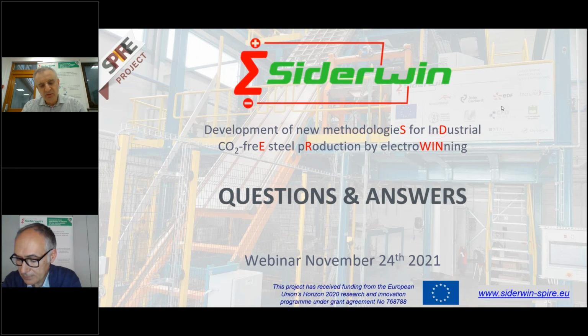Also, I think Sevasti has well presented the fact that iron is a good candidate for application of electricity. At the start of this development, iron with its multivalencies was considered a complex element to be treated by electrochemistry, but with the treatment of the iron oxide by this specific route in alkaline condition, we can achieve a good transfer of electricity into iron metal, and we expect with this property to be more energy efficient than the hydrogen route. But also the direct reduction by electricity has a TRL, a technological maturity, which is much lower than the hydrogen route, which capitalizes on the DRI, the direct reduced iron.